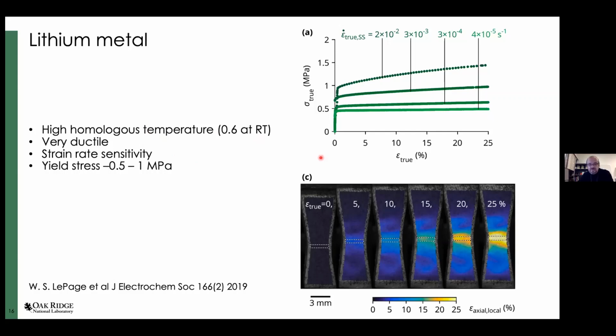These are the tensile tests that were done on the metallic lithium ribbon. With digital image correlation, you can see a lot of necking. It can take a lot of strain, and it flows plastically very beautifully. And in bulk form, its yield stress is from 0.5 megapascal to 1 megapascal. Basically, anyone who builds a half coin cell with lithium metal knows that it pretty much spreads almost like butter in its bulk form.